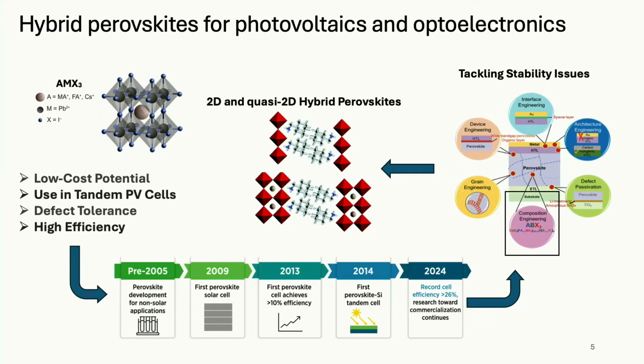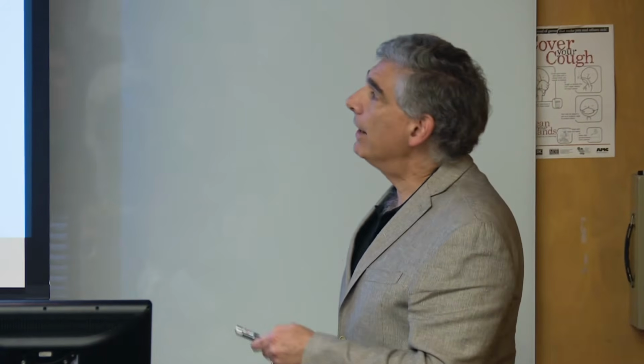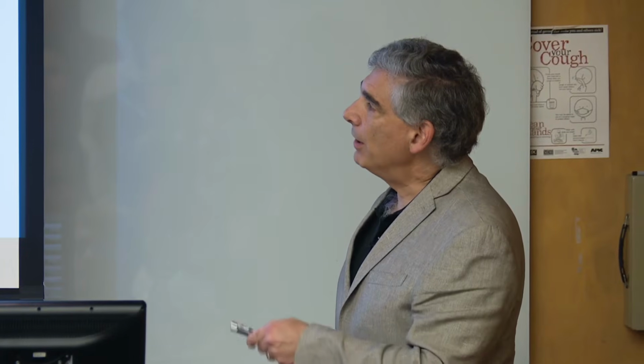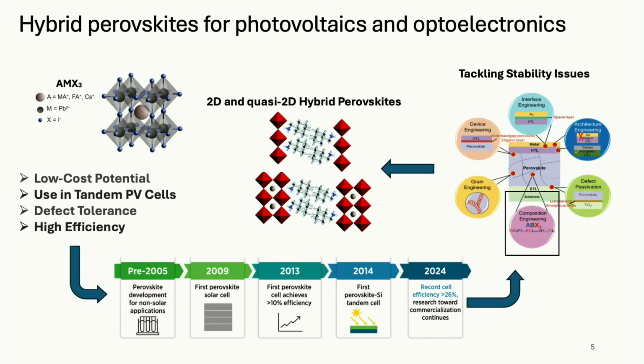So one theme of my remarks will be a clever development over the last decade or so: to move from the 3-dimensional cubic perovskite structure to layered or 2-dimensional perovskite structures, where you have a certain number of layers that definitely look perovskite-like, but then there's a large molecular spacer layer in between, and then the crystal repeats. It turns out that by making this kind of hybrid structure, there's so much more hydrophobic molecular species, that these seem to have much better stability. And so it's a promising new direction to find a sweet spot of favorable optoelectronics and beneficial stability.